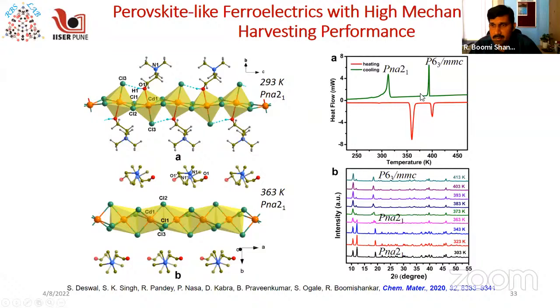But at a higher temperature of 400 Kelvin, the molecule becomes centrosymmetric. That means that it is going from the ferroelectric to the paraelectric phase.